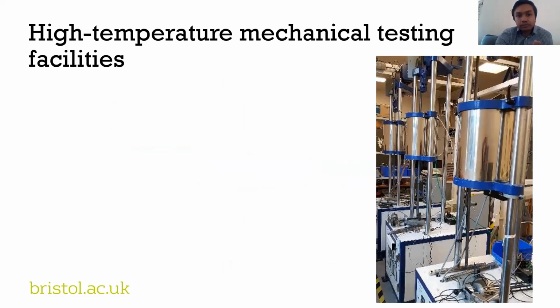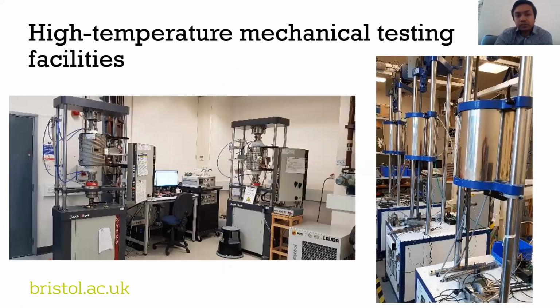So for mechanical or macroscopic deformation, we have this amazing facility here in Bristol. We have high temperature mechanical testing machines, including a creep machine where we can do a dead load type of simple creep test at temperature. But we also have a really sophisticated mechanical tester where we can simulate the different loading conditions that this material experiences in a nuclear power plant, for example. It has a high temperature furnace, and there is a variety of loading, a variety of rates and a variety of temperatures that we can apply. So this gives us a way to validate our model using this macroscopic data.